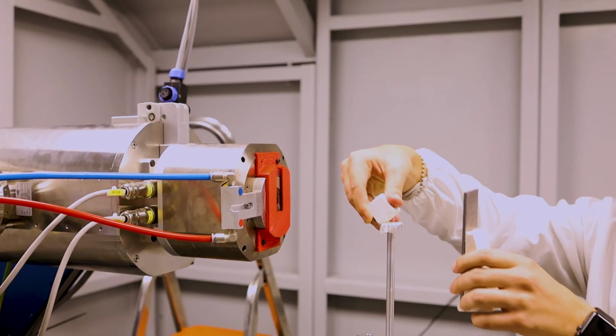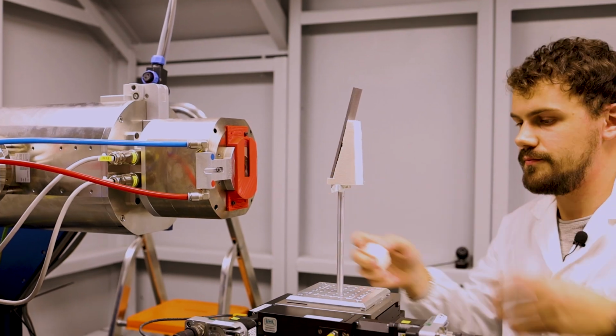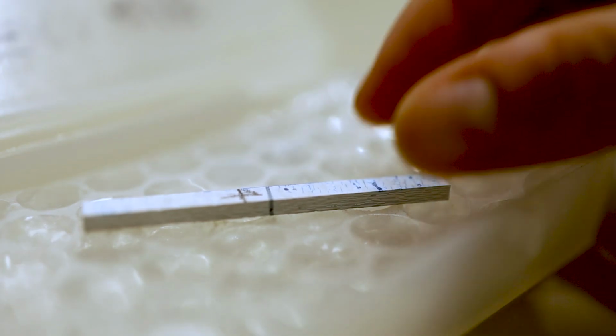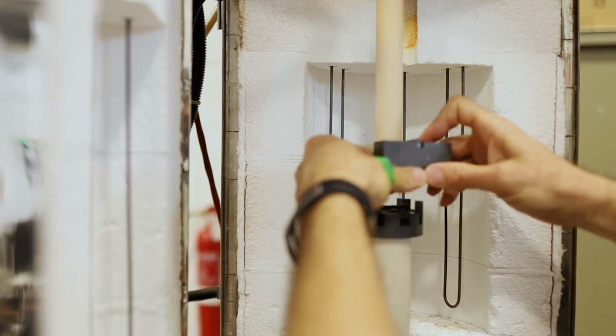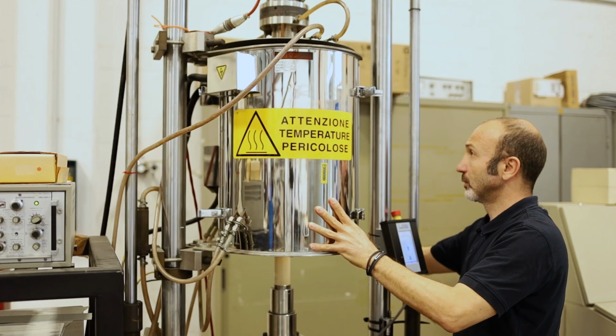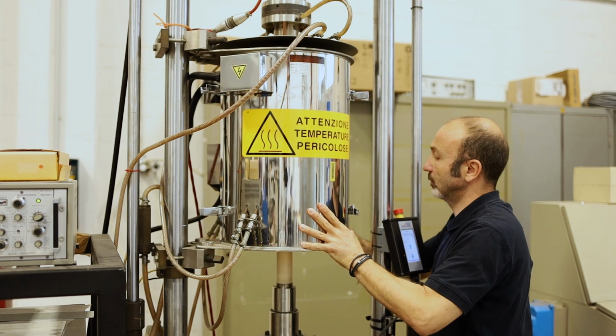Different tests were performed to measure the emissivity of the materials to deduce heat exchanged by radiation, and the performance of the materials was assessed after aging in representative atmospheres containing carbon dioxide, water vapor, and nitrogen. And we could check that the combination of them would give something understandable. This is already one point, and the other point is that we checked too that we could understand exactly the rate of material transformation at its surface and internal surface area by the effect of oxidation or corrosion.